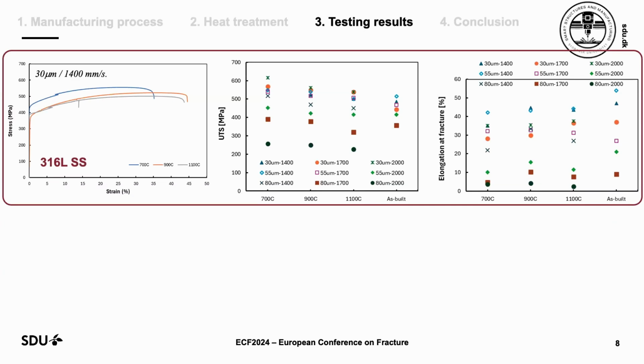For the case with layer thickness of 30 micrometer and a scanning speed of 1400 for the stainless steel, we can see the effect of heat treatment. As we increase the heat treatment temperature, we have better ductility but reduced strength. This is in accordance with the literature, and this is mainly because of the change in the grain size and also dislocation. When we do the heat treatment, recrystallization is happening. Of course, at different temperatures we don't see the same recrystallization; at 700, 900, and 1100 it is different, but we see recrystallization in different order, and also reorientation and decreasing of the dislocation, and that reduces the tensile strength but increases the ductility of the material.